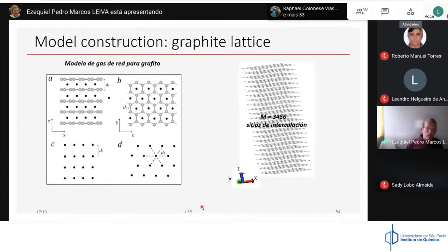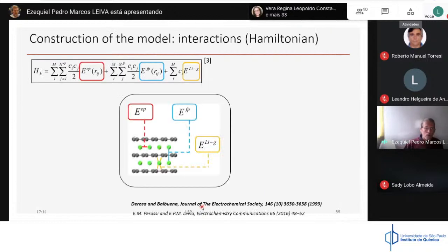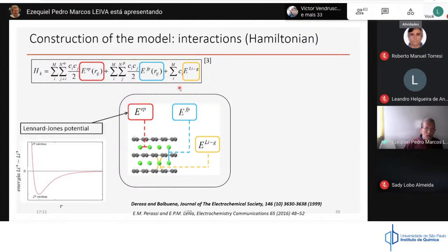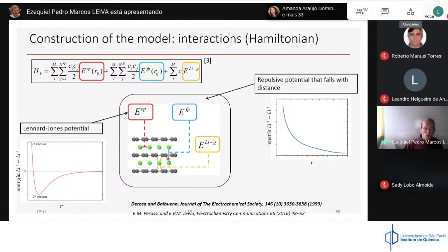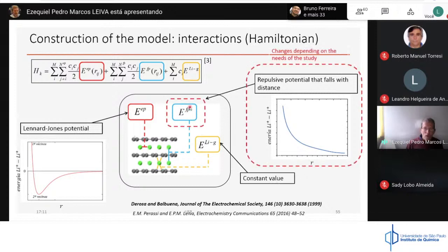The first thing is that this is not molecular dynamics, we use a lattice system. And you have to use a Hamiltonian to describe the interaction between the particles of the system. This Hamiltonian contains terms relative to the interaction between the lithium ions, as I show here. And you also have interaction terms between lithium atoms in different layers, and these are repulsive. So you have a part of this potential which is attractive, due to the interaction of lithium ions in the same layer, and you have a repulsive contribution from the interaction between lithium ions in different layers. Once you have a Hamiltonian and a lattice, you can calculate.